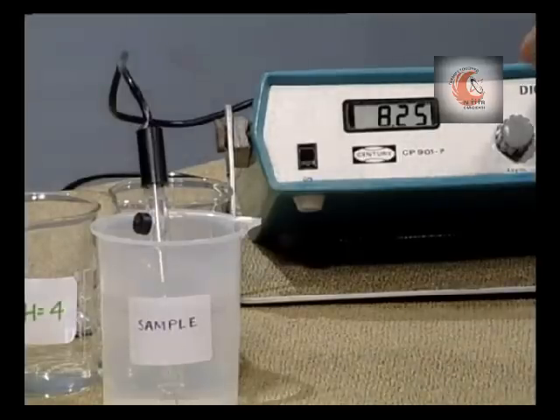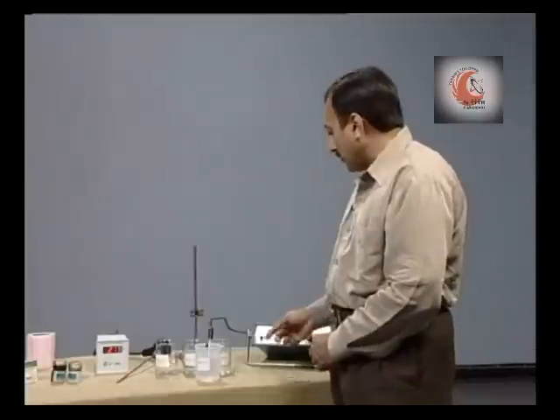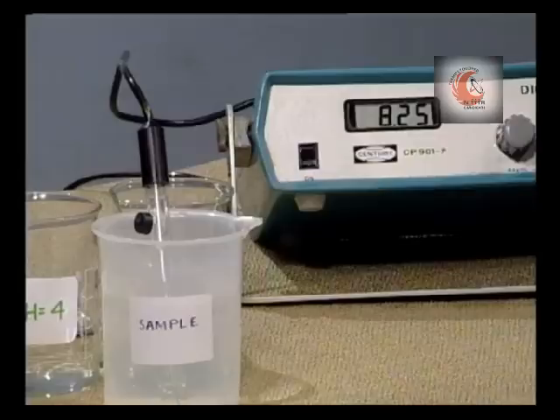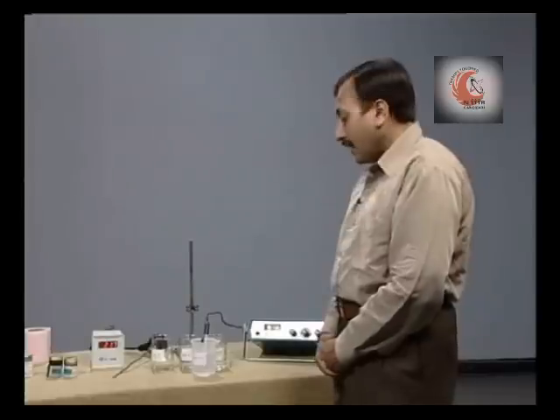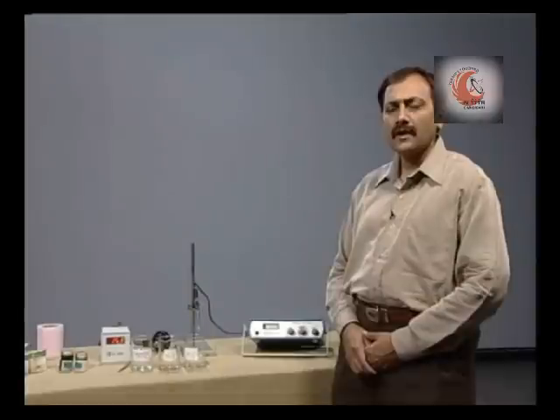So, we can note down this value. The pH value of this sample is 8.25. This is well within the acceptable limit of 8.5. Thereby, this water from the pH consideration is fit for consumption.